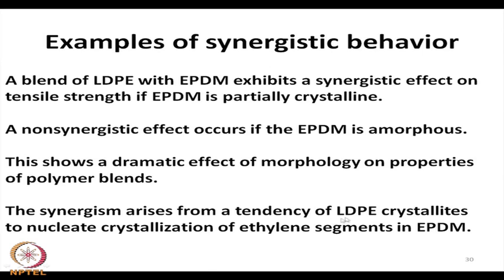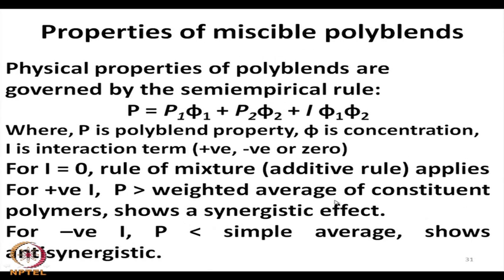This is a very interesting observation, that since LDPE is crystalline, that LDPE crystallite will induce or nucleate some crystallization in the ethylene segments of the EPDM polymer. That is why the synergistic effect is available. Now, the properties of miscible polyblends can also be explained in another way.